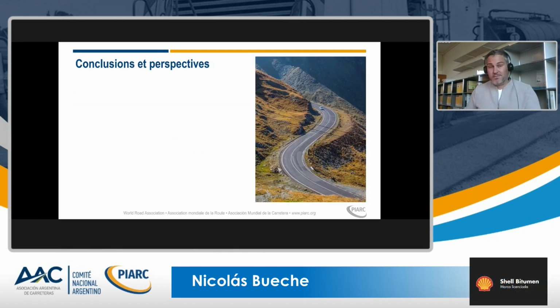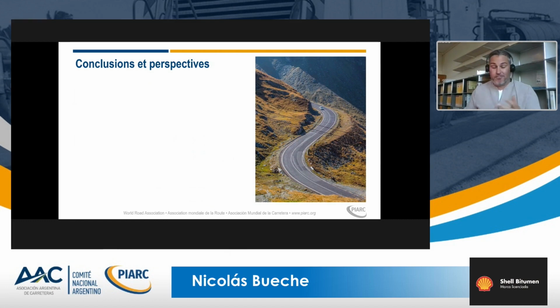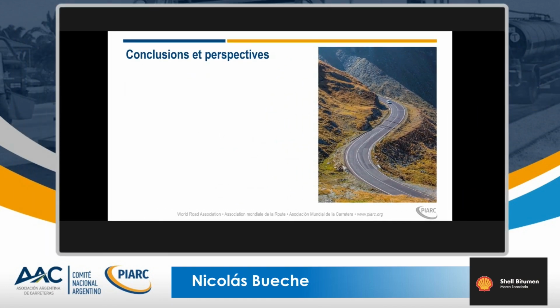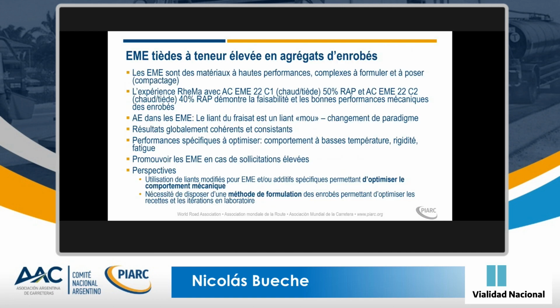Now I come up to some conclusion, some perspective. Once again, it's only a Swiss perspective. We are a very small country, so I cannot say that what we do can be applicable to every country. But I think the first one, which is really important, in the project, we could demonstrate that we can produce high modulus asphalt, so with very high stiffness, good fatigue resistance, including 40 or 50% RAP, and produce it in a warm mix process without major problem. This can be done. This is no problem, and we could do it in the framework of this project, and we could, let's say, demonstrate the feasibility.